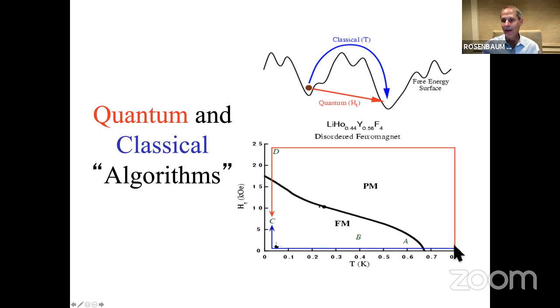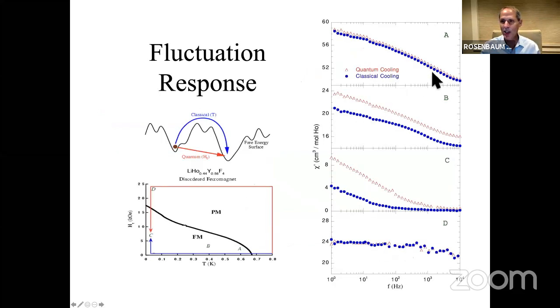And I'm going to do that for a number of different points. I'm going to look just inside the phase boundary. I'm going to look a little deeper. I'm going to look very deep in the phase boundary at 30 millikelvin. And then I'm going to look in the paramagnet for a sanity check. Okay, so that's what you're seeing here. Point A is just inside the phase boundary where I have lots of thermal fluctuations. And you can see there's not much change.